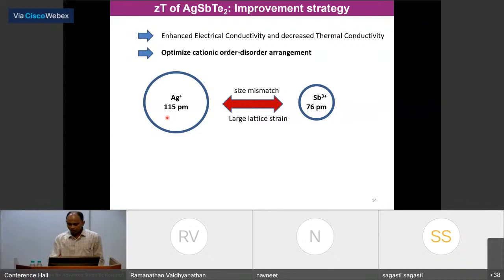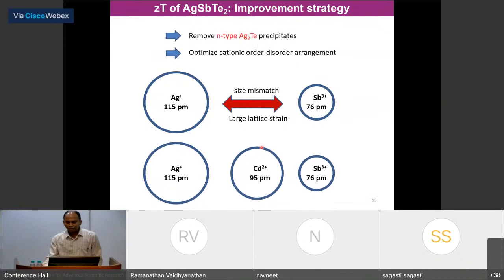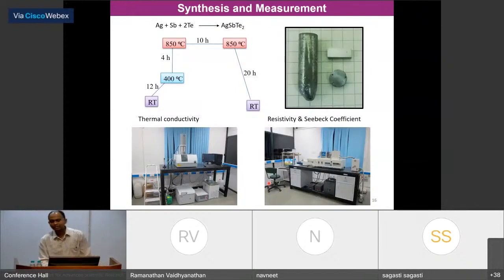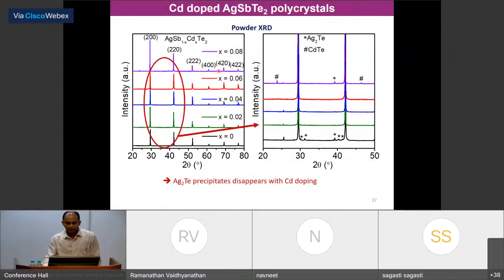So we searched the periodic table, because we know the periodic table like the palm of our hand. We chose cadmium 2 plus, which is exactly the average size. If you add 115 and 76 and divide by 2, it's basically 95 or 96. So we chose cadmium and doped cadmium purposefully into this compound. Let's see what happens. We synthesized this compound by a vacuum sealed tube reaction, and I'm not going to go into the details of that.